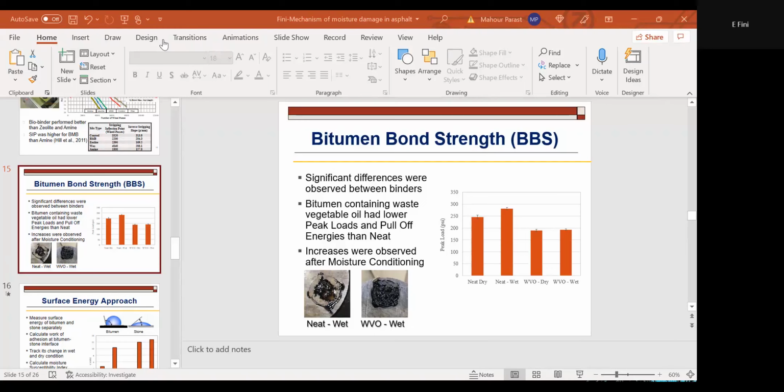I'm talking about chemistry-driven moisture damage, where you have molecules that cause weakness at the interface of the bitumen and substrate. At a very small scale, your substrate can actually be those mineral fillers, which are passing sieve 200. So very, very tiny mineral filler is still the first point of contact with bitumen, where the filler gets coated with bitumen. If the filler-bitumen interface has molecules that are soluble and make bad bridges, the first crack, or initiation of the crack, will be right there at the interface of the bitumen and mineral filler.